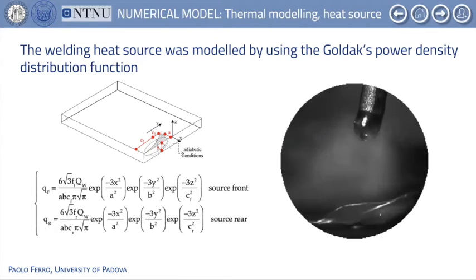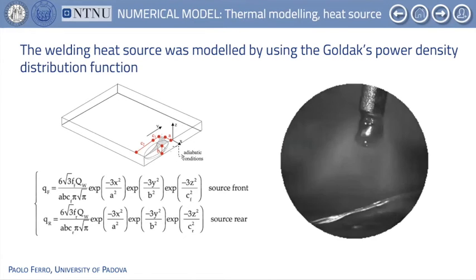Sequentially, the thermometallurgical-mechanical uncoupled simulation was carried out, where a dedicated function was employed to set the mechanical properties of the material to 0 in all nodes where the computed temperature was higher than the melting point. Moreover, isostatic clamping conditions were applied during and after welding.